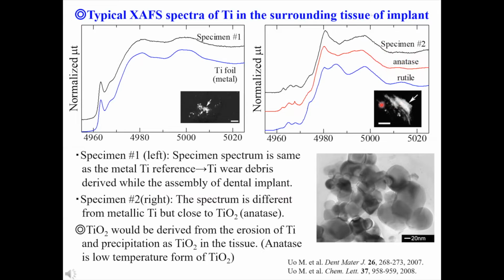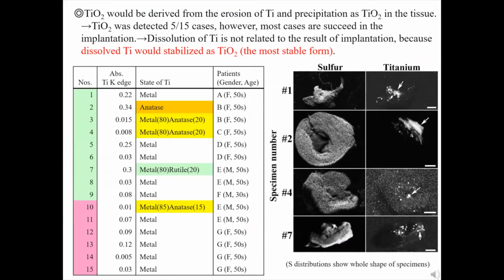This implant is a conventional Brånemark type 2 implant, which has a machined metallic surface. Then, the derivation of this oxide should be discussed. This table shows the results of XAFS analysis of 15 specimens. Specimens 1 to 9 were derived from the oral mucosae in contact with the pure titanium cover screw through the ordinary second surgery. Specimens 10 to 15 were derived from the surrounding tissues of retrieved implants. The chemical state of titanium can be estimated by comparing the XAFS spectra to those of reference compounds. Metallic titanium was mostly suggested; however, titanium oxides were also detected in some cases.